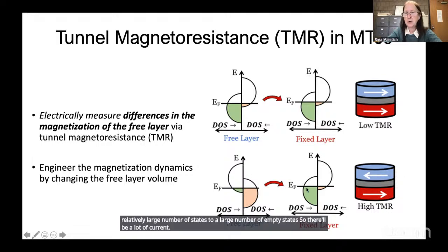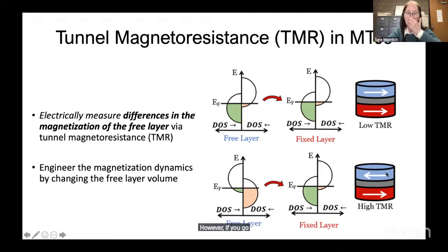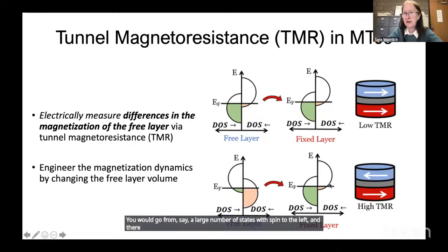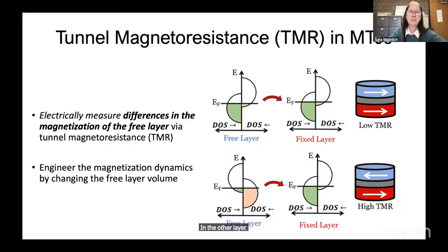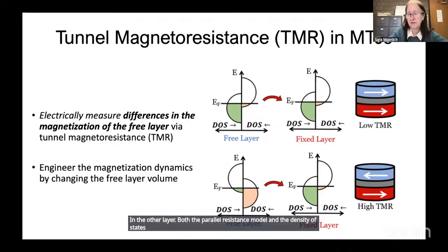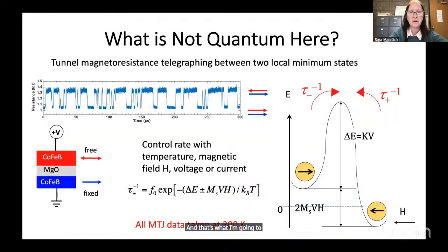However, if you go to a layer that has the opposite magnetization, you would go from, say, a large number of states with spin to the left, and there's not as many states available to go into in the other layer. So both the parallel resistance model and the density of states model explain the difference in resistance depending on whether the magnetization of these layers are parallel or anti-parallel. And that's what I'm going to build on in the rest of the talk.